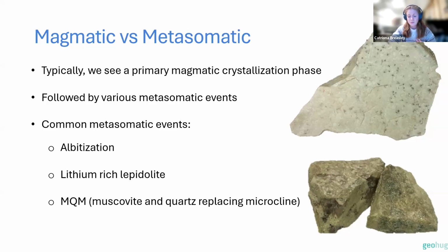And metasomatism is really important in pegmatites and being able to distinguish these features because they can act to concentrate or deplete elements, which is going to affect the economic viability of your deposits at the end of the day. So I've put two rock samples on the screen here, the upper of which shows the aplite albite zone from Tanco, which is quite debated, but I personally think it's a secondary overprint, and this shows enrichments of tantalum, and that's one of the main zones that Tanco targets for mining of tantalum. And also on the bottom here, muscovite and quartz also has elevated tantalum at the Tanco pegmatite as well.